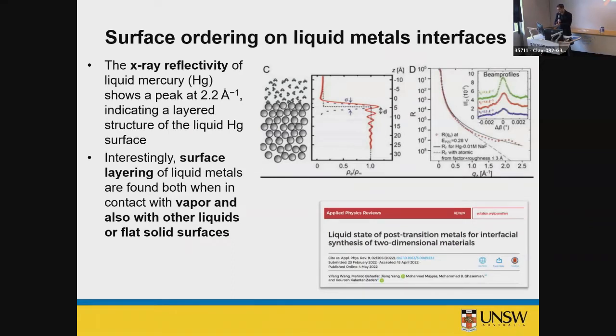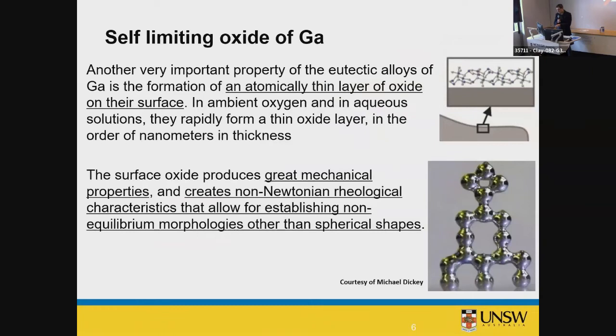Okay, let me go back and go forward. Good. So this ordering is very helpful. So when you expose gallium or other post-transition metals to ambient conditions, for instance, water vapor in the environment or oxygen in the environment, they oxidize. And this oxidation produces very highly ordered, sometimes not highly ordered, depends on the state of liquid that you're using, two-dimensional materials. So that's where we go towards two-dimensional materials. Gallium oxide is produced like graphene, like other two-dimensional materials.